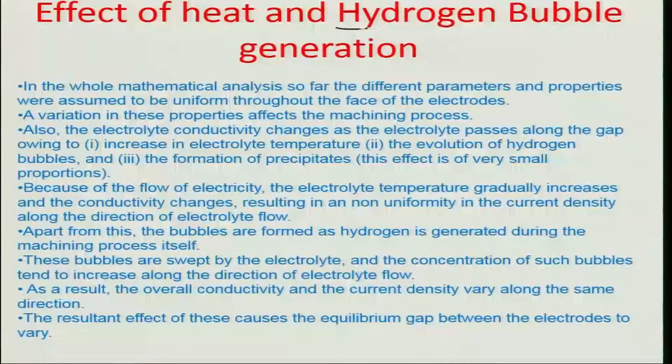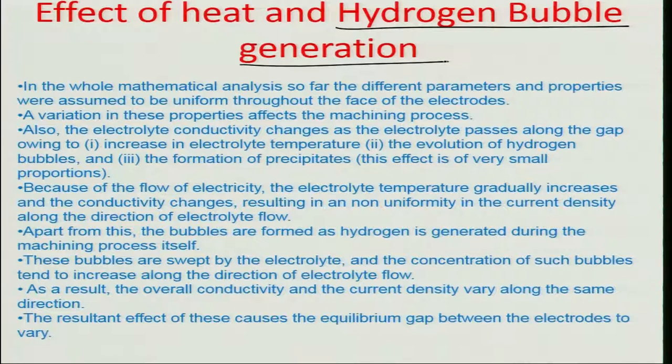Today we are going to discuss a different aspect of ECM. One part is that when heating increases there is electrolyte boiling, but there is a very important secondary aspect: hydrogen bubble generation that changes the conductivity drastically of an ECM setup, and therefore there are changes related to machining rates because the conductivity differs based on wherever these hydrogen bubbles are generated.